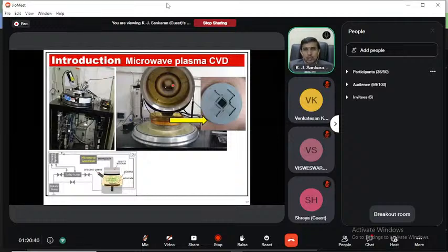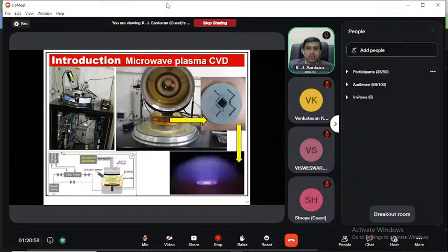evacuated, so the unwanted gases are removed. Once it reaches more than 10 to the power minus 6 Torr, we can start passing our needed gases like methane, hydrogen, argon, and nitrogen inside the chamber. Then the microwave is started, which ionizes the gases and creates the plasma here. So this is the plasma formed by the methane and hydrogen gas. You can see the silicon substrate here, and the diamond starts growing on the silicon substrate.